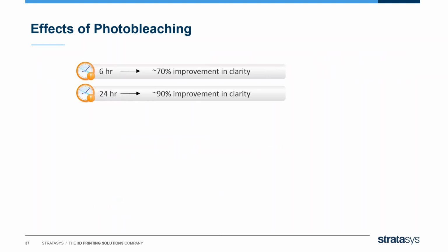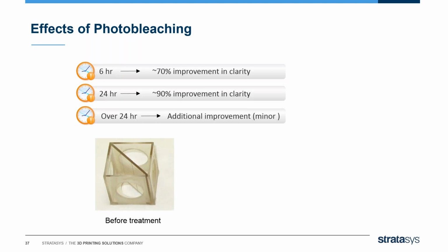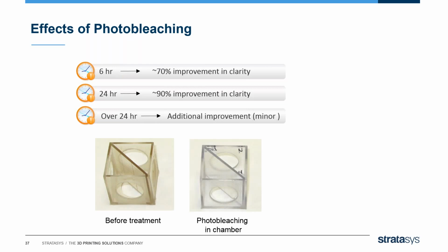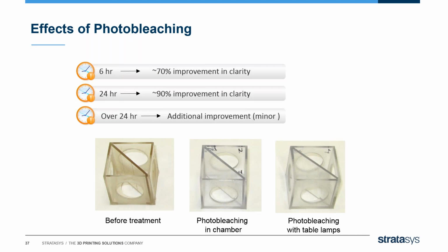So what are the effects of photo bleaching? After 6 hours, we can already see a 70% improvement in clarity. After 24 hours, we see about a 90% improvement in clarity. Anything over 24 hours is pretty minor for improvement. So our recommendation is typically to let it sit for 24 hours in an illumination chamber to get the maximum clarity out of the part. Here's an example of a part before treatment, photo bleaching in a chamber, and then photo bleaching with table lamps. As you can see, the photo bleaching in the chamber exhibits the best results, which would be expected.